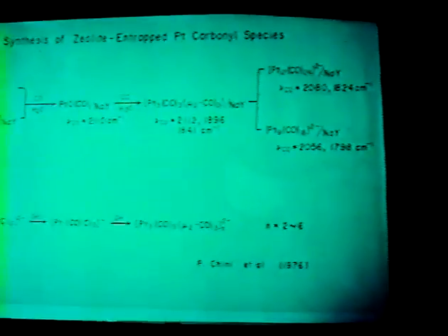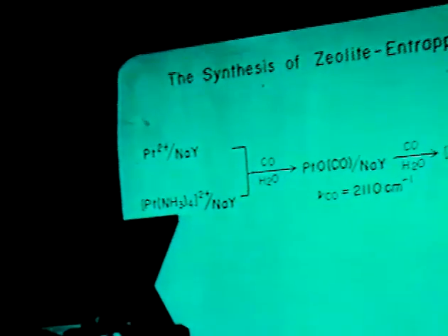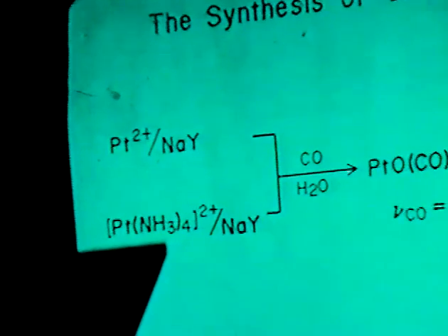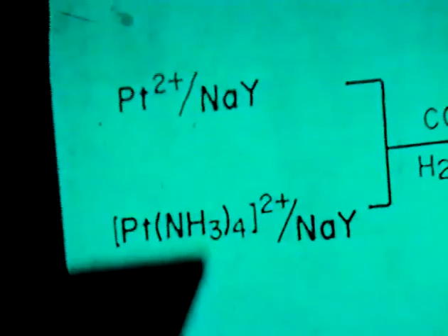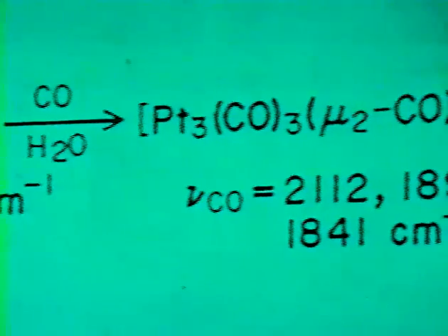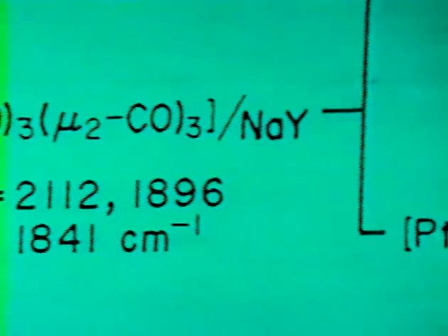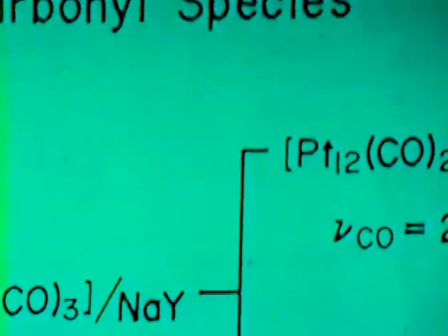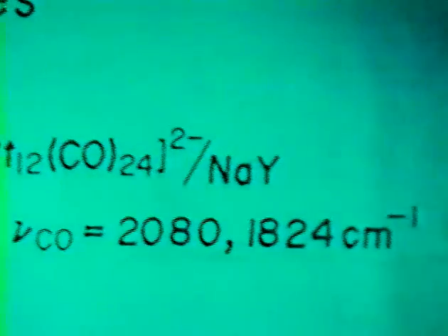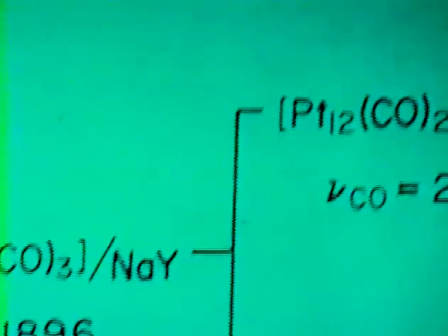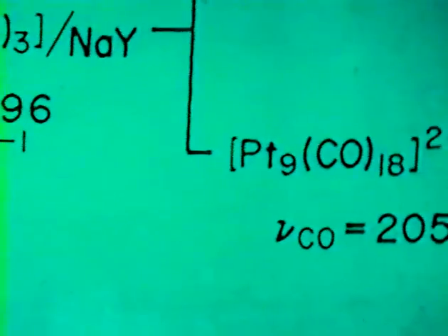This kind of successive formation of the carbonyl species from mono carbonyls, metal carbonyls to triangular carbonyls, and up to just the prismatic cluster species, which accommodate sodium ions. It's quite a good analogy of the solution chemistry starting from the platinum source in methanol solution by controlling the base properties, which was reported by chemists in old times.